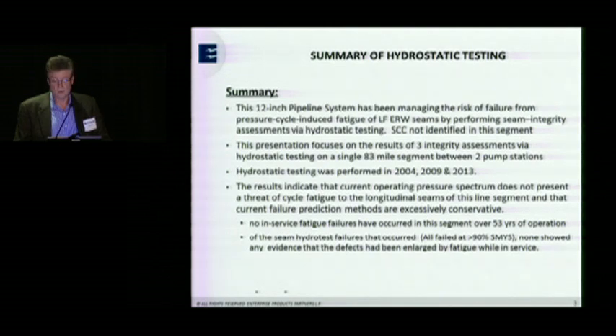Hydrostatic testing was performed in 2004, 2009, and 2013. And in summary, based on those hydrostatic tests, we have had failures. All of those failures occurred at pressures greater than 90% SMYS. We did get some pressure reversals, but in none of those instances was there any fatigue growth measured on any of these failures.